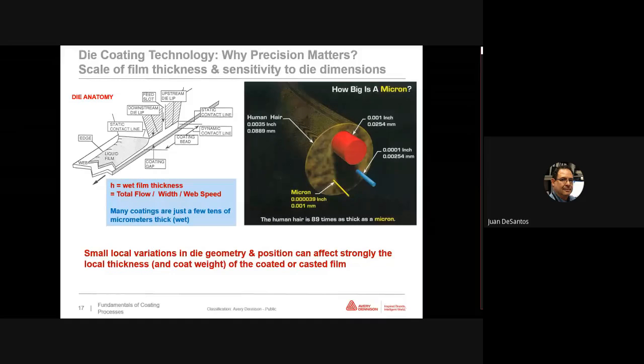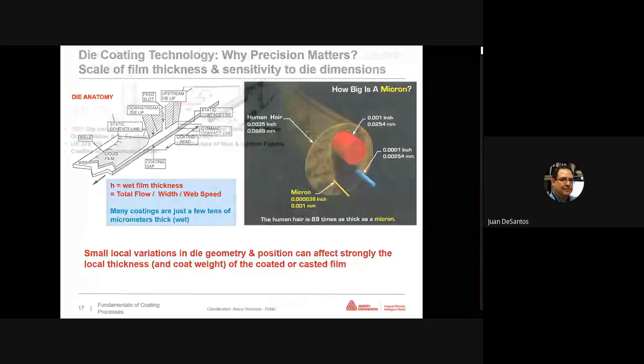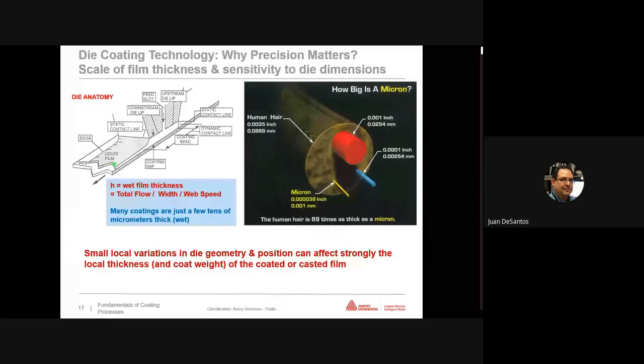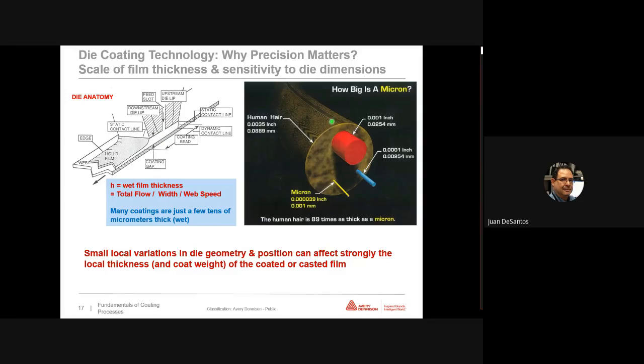Now, precision matters because you have films that are 10 to 100 microns and similar dimensions in the bead and in the slot. To give an idea of what this means, this schematic represents a human hair, which is about 90 microns. We are looking for precisions close to 1 micron, which I show here. The reason we need such high precision is because small variations in die geometry and position can strongly affect the local thickness and coat weight of the coated or cast film. That's the reason why these methods are better, but they are more expensive.